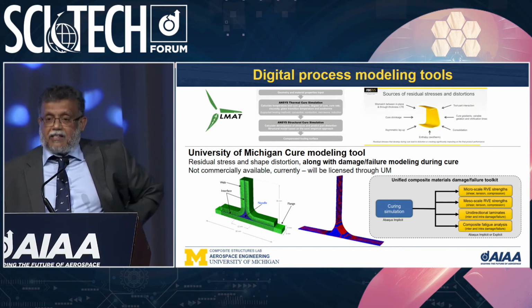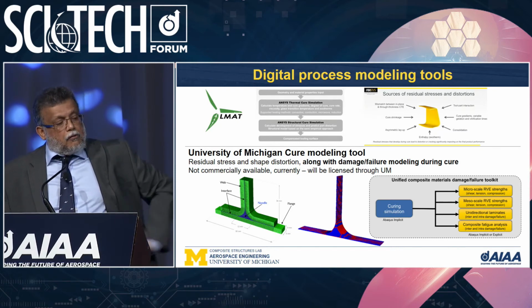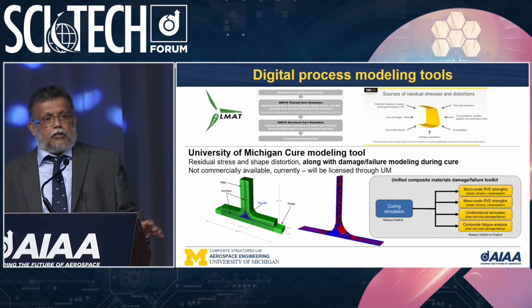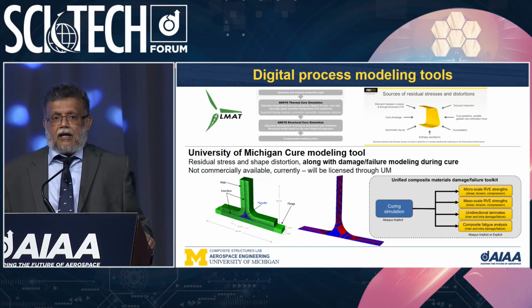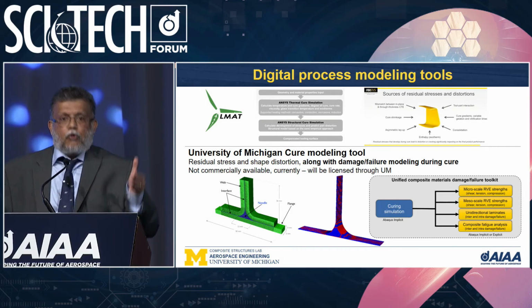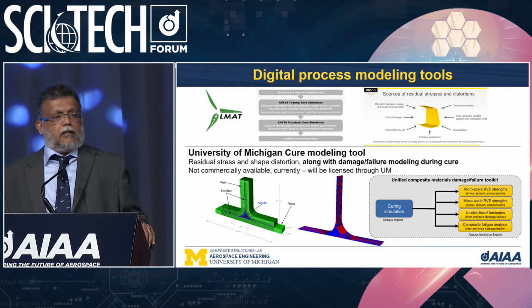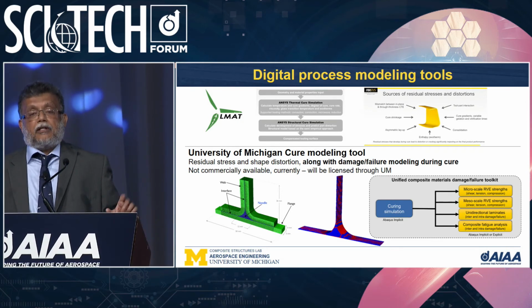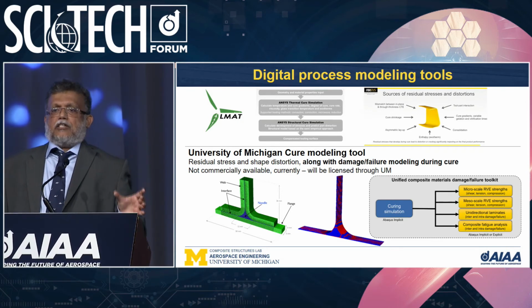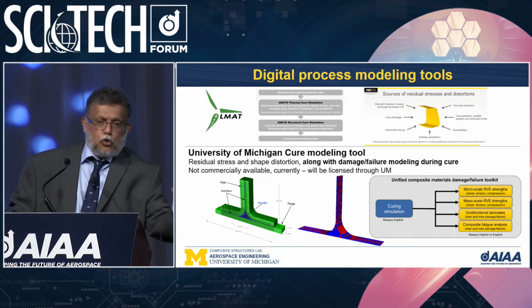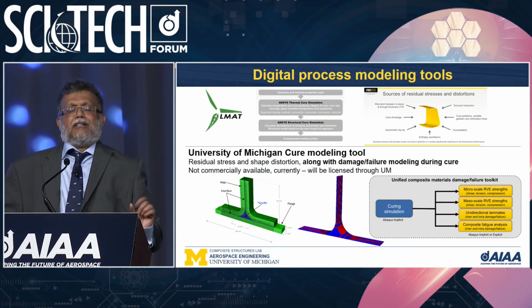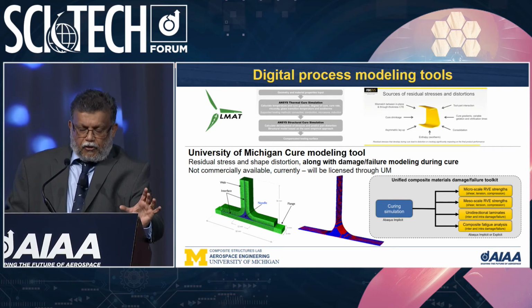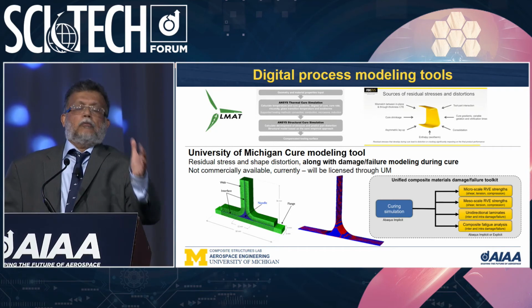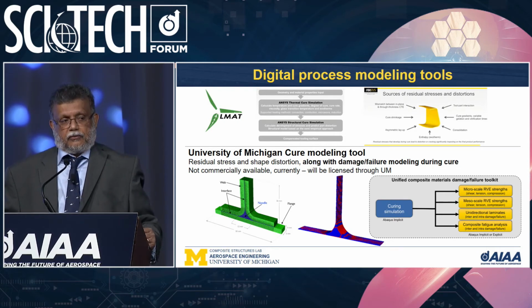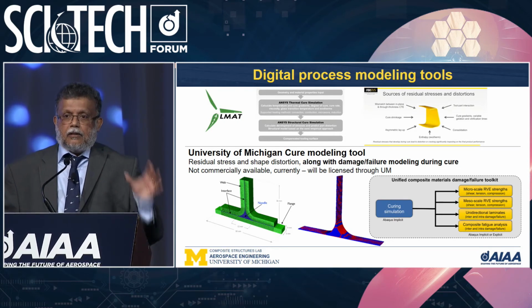Here I'm showing an illustrative example of a famous noodle problem, where I used an exaggerated cure cycle to show how cracking can start near the noodle and then progress up. But if you change the cure cycle, you can suppress that cracking during the curing process. So the advantage of a digital tool is that you can do these trade studies to optimize your cure cycle for the particular structure before you set the manufacturing process. That's the reason you want to analyze shape distortion and damage during the cure process.